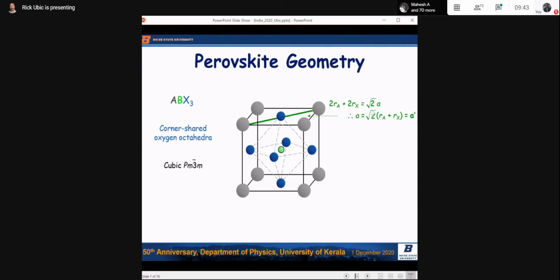Okay, so we can solve this equation for a, the lattice constant: a equals the square root of 2 times the AX bond length, and we'll call that value a prime. Here we go, a prime. Right? That's one way of defining the lattice constant. Another way is going across the body center this way. So that's 2 BX bond lengths, 2R_X + 2R_B equal to the lattice constant. We solve that, of course, right?